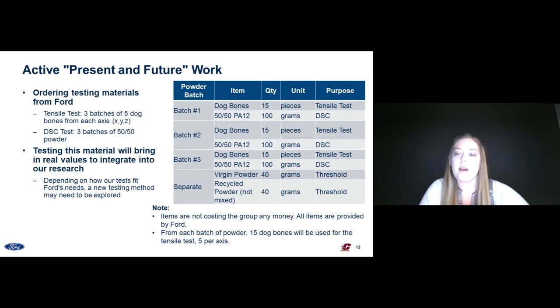Z. And then for the DSC test, we will be using 50/50 powder, since that is what Ford uses currently. We've requested 100 grams of that powder for each of our 3 batches. And then separately, we've ordered 40 grams of virgin powder and 40 grams of recycled powder. These materials will be used as baselines and thresholds in order to compare our thermally degraded powder with the virgin and recycled powder.